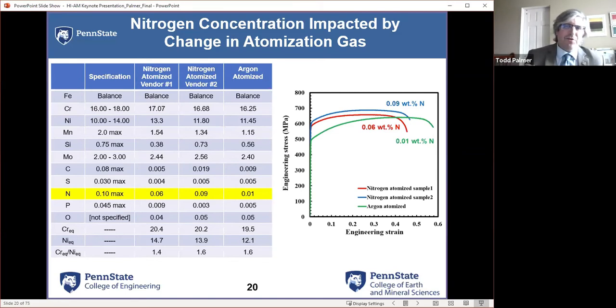Nitrogen is really a well-known austenite stabilizer. We're going to see when I start talking about the PH grade stainlesses that this is a big deal. And even here we see, these are just some engineering stress strain curves. Low nitrogen levels, that's pretty significant, over 100 megapascals in yield strength, and probably right around the same, maybe a little less, in ultimate tensile. There are some real differences in just how we atomize the powder, but if I were to just buy these powders as an idea of meeting the specs, I would tend to assume that they were all the same.